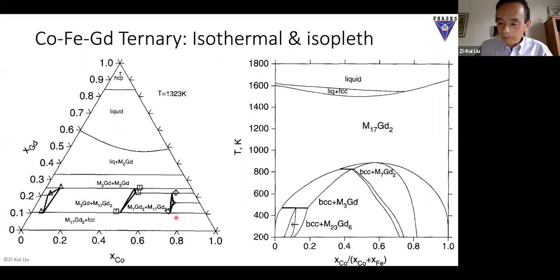But this way, you can see the feature that, for example, if you want to make this alloy at this composition, you have to make sure you heat treat at high temperature and then quench it down. If you do low temperature, you're going to form different phases, because this gives you the process design.